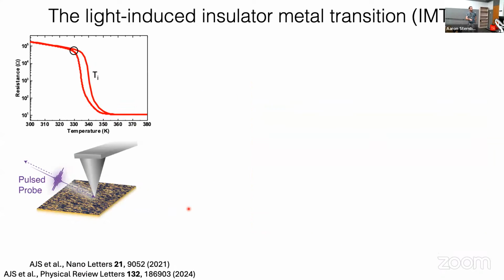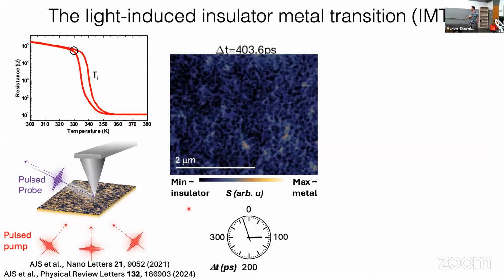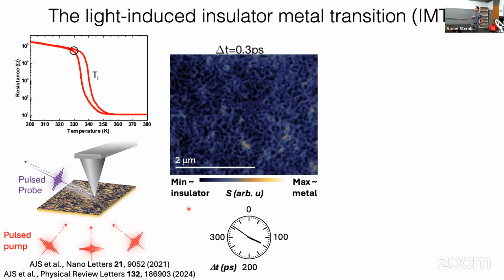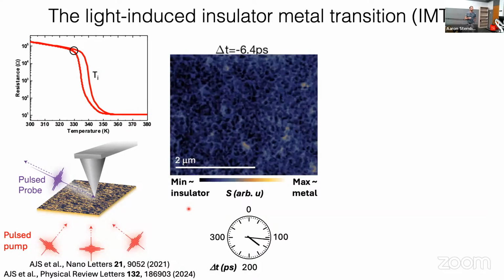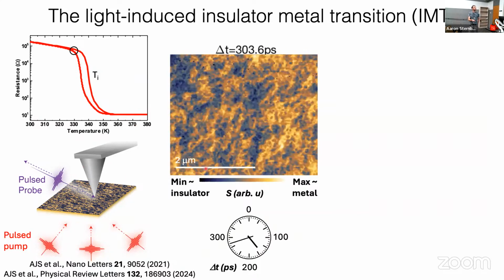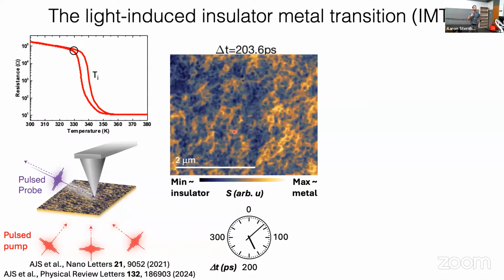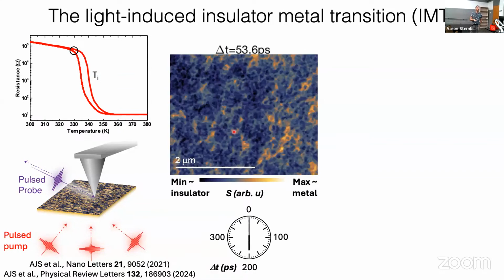What we've done is to adapt this measurement to operate with pulsed sources. So we're measuring these maps now with a pulse of light that arrives in a 200 femtosecond burst, and that allows us to initiate the transition with another pulse of light and monitor how these images evolve as we change the pump probe time delay. And what we can see is that the transition is clearly inhomogeneous and evolves over a timescale of hundreds of picoseconds.